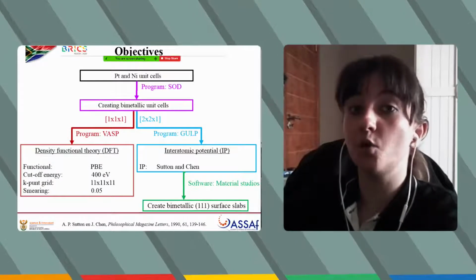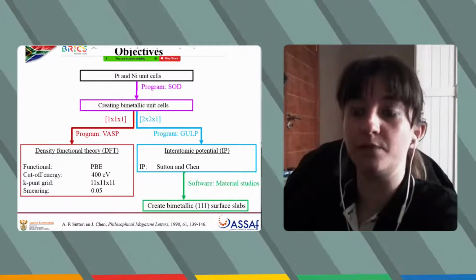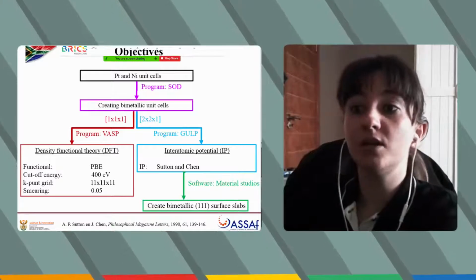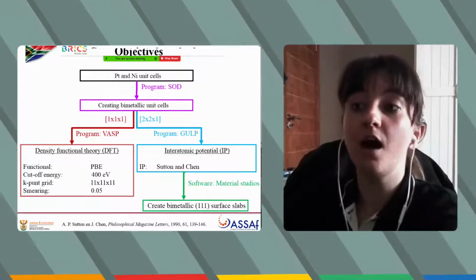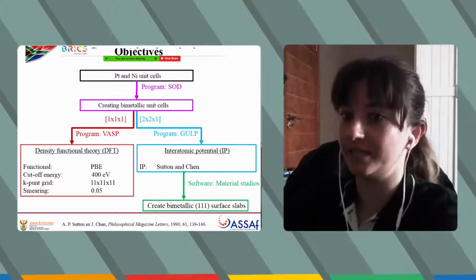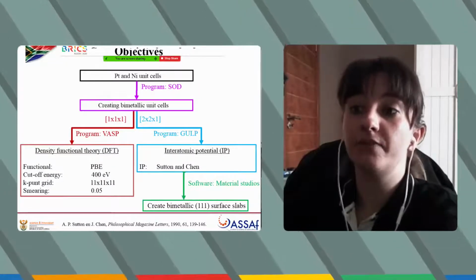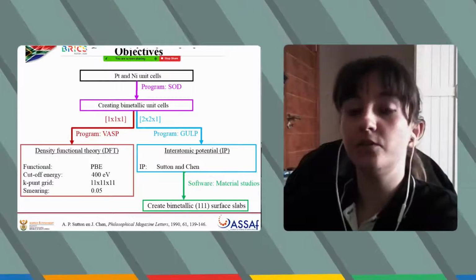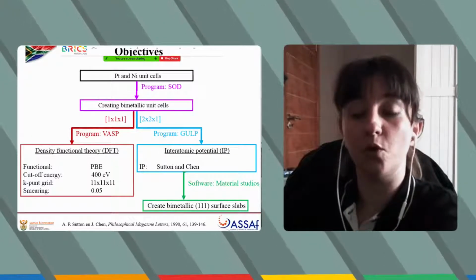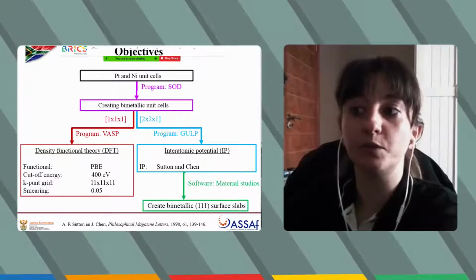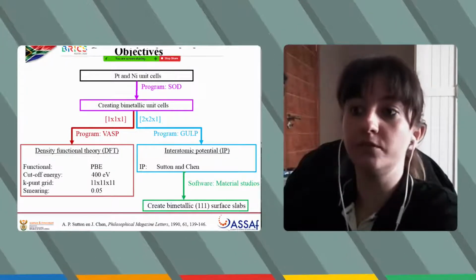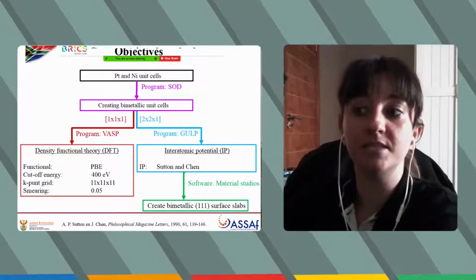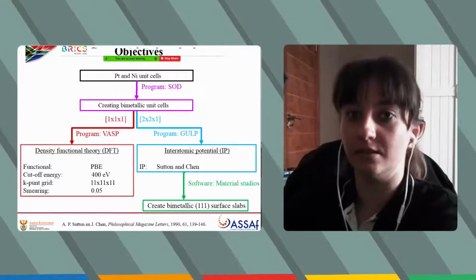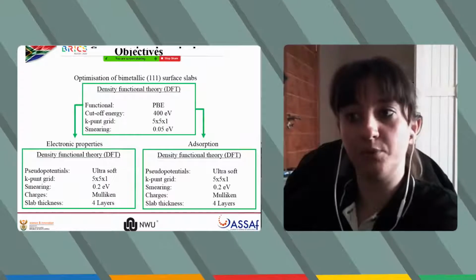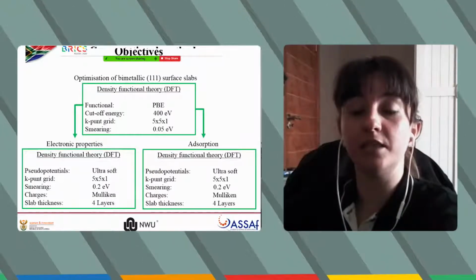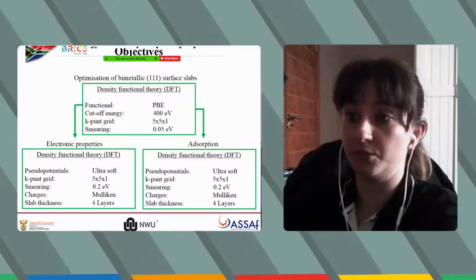Within this model, the site occupancy disorder program was used to create bimetallic unit cells. The smaller cell was optimized using the Vienna ab initio simulation program as indicated. Due to the large number of atoms in the large cell, the general utility lattice program was used along with Sutton and Chen interatomic potentials. Furthermore, Material Studio software was used to create bimetallic slabs from the larger cells. The bimetallic slab optimization, the electronic properties, and the adsorption properties were calculated from the settings shown.